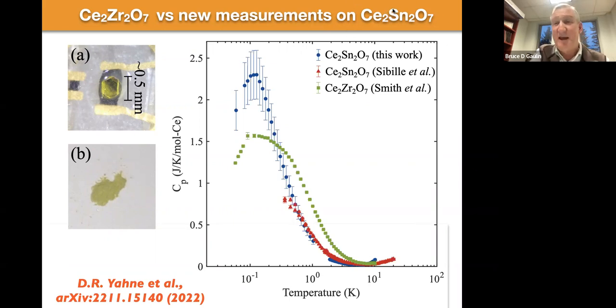One of the inorganic chemists that we work with, Joe Colas at Clemson, has been also growing pyrochlores, these types of pyrochlores. But he's been doing it by hydrothermal techniques rather than solid state synthesis. So this is very different from what we do. It has certain advantages in that the growth is at lower temperatures. You're basically growing it out of hot water. That's a bit of an exaggeration, but the net result is that it helps with the problem of the volatility of the tin in cerium tin oxide.